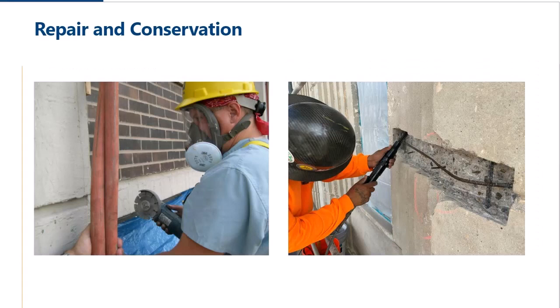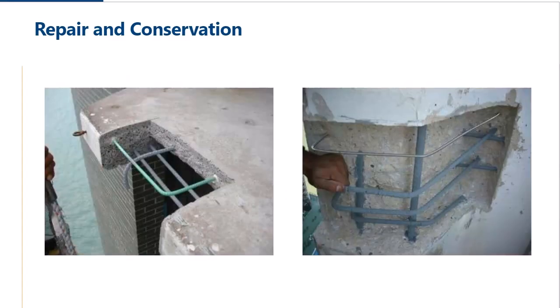The first step is to remove concrete to address the repair area and deterioration mechanism. With heritage concrete, we don't want to remove sound concrete — nobody likes to lose historic fabric — but you really do have to remove sound concrete to be able to address the deterioration mechanisms. Removing sound concrete to get all the way behind the bar is critical. Regarding reinforcement, sometimes supplemental reinforcement is needed — addressing what's there, whether it has loss of section, arresting ongoing corrosion, and sometimes adding supplemental reinforcement for a good mechanical bond of the repair material.